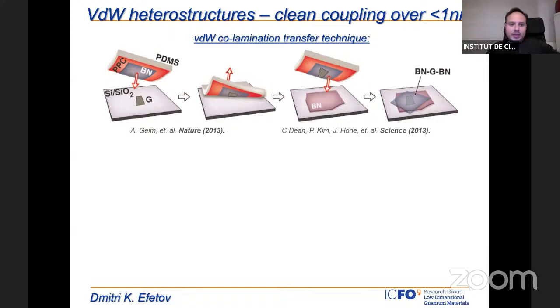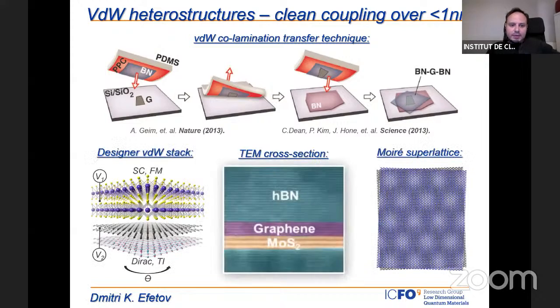This illustrates the process we do. We can exfoliate layers of graphene, this two-dimensional sheet which sits on a substrate, and then we can stamp it with hexagonal boron nitride layers, which are basically the insulating form of graphene. With this process, we can assemble them one on top of another. In the end, we really end up with these heterostructures, and we can assemble them one after the next. So this gives us an opportunity to, starting from those two-dimensional layers, assemble any type of combination of material we like. In principle, we can assemble insulators, metals, superconductors, ferromagnets, and we can assemble them in these stacks.